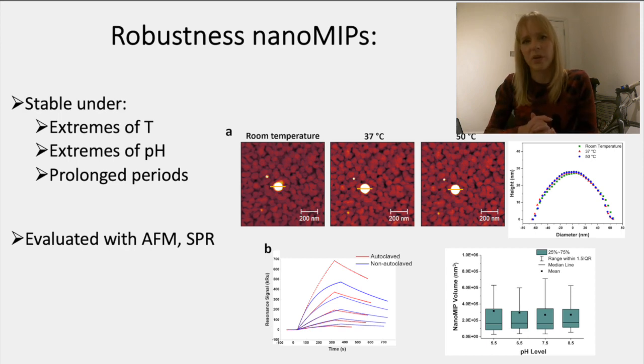Obviously this is very beneficial because it means that you might be able to store the material for a very long time, even when it's in solution. Then also using atomic force microscopy, we showed that there really wasn't a change in the shape of the nanoparticles when we exposed them to elevated temperatures up to 50 degrees or to extremes of pH. Because we knew there were problems when you, for instance, expose antibodies to acidic media, such as what you've seen in lateral flow tests when people were using, for instance, Diet Coke to interfere with the measurement results. And clearly it turned out it wasn't just the shape that wasn't affected, but these nanoparticles also retained their affinity even within these conditions. And that eventually might open up some interesting prospects if we wanted to measure in some challenging environments.